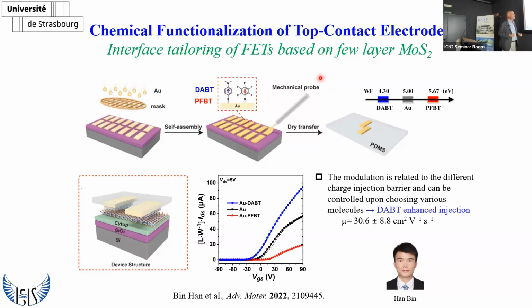To prove that this has an effect on the field effect transistor, once he has the electrode functionalized, he takes it with a micromanipulator, turns it upside down, and lands it on the surface of the semiconductor, okay? And I have statistics of hundreds of devices, so it is highly reproducible by him. To the point that he can also put the electrodes very close by. The closest channel he reached was 7 nanometers by hand. Okay, so I told him that he is doing the wrong job. He should go to work for Rolex and become rich instead of being a chemist. But okay, that's his problem.